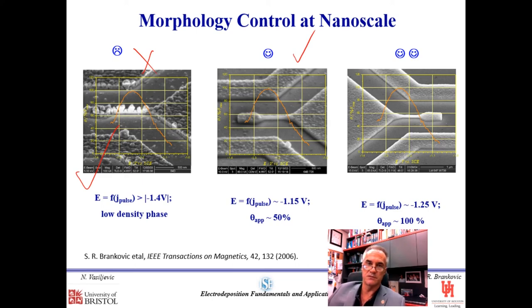These structures eventually will result in a device which is performing, but not so much yet satisfactory. And eventually, if we design the process and tune the pulse current density, so the potential of the surface is in about the region where the PZC is, which is about 100% coverage, then you can see the structures look perfect and this device performs well.